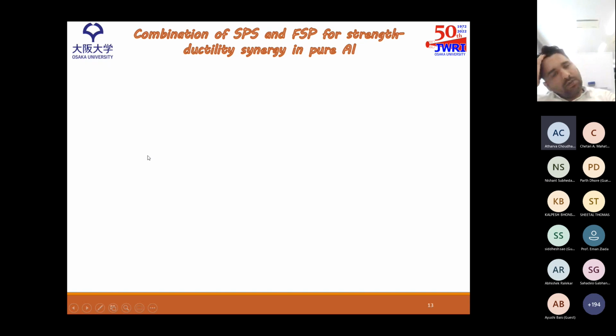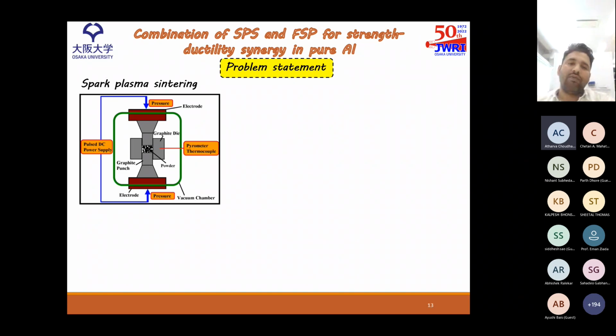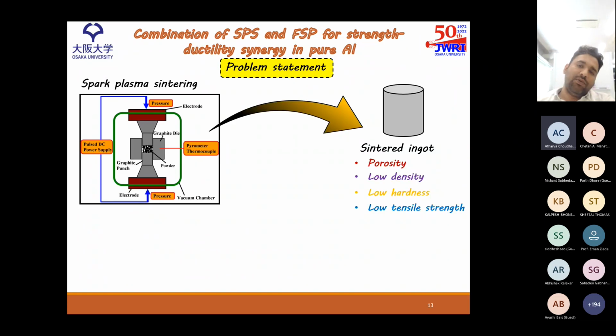Now coming to the second part of the presentation, this is my second project, where we have combined spark plasma sintering and friction stir processing. Now why are we combining these two advanced manufacturing strategies? The reason is that when the powder billet is formed with SPS, it has some porosity. It is 95% dense, but still there are 5 to 10% chances of porosity. This porosity reduces the density of the component and the hardness as well as the tensile strength.